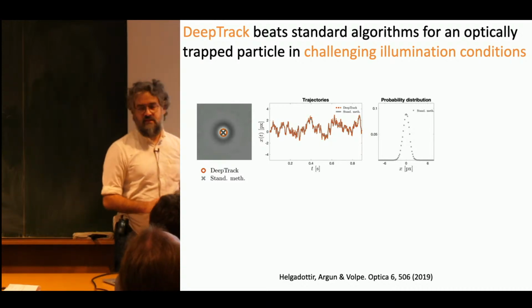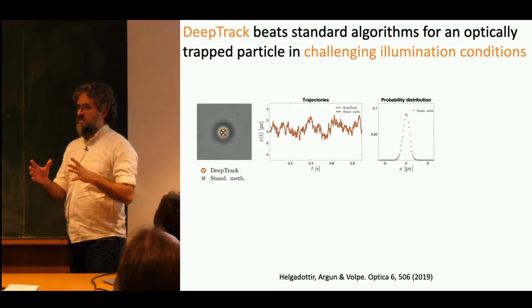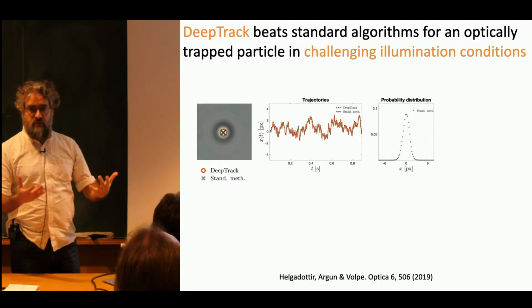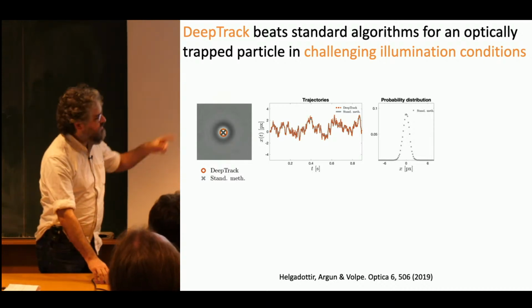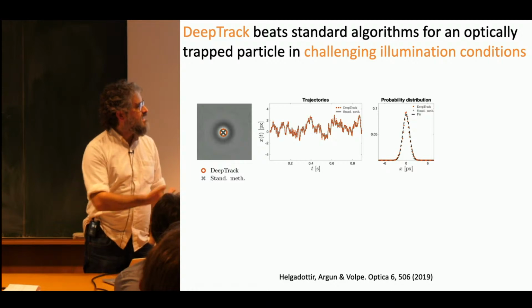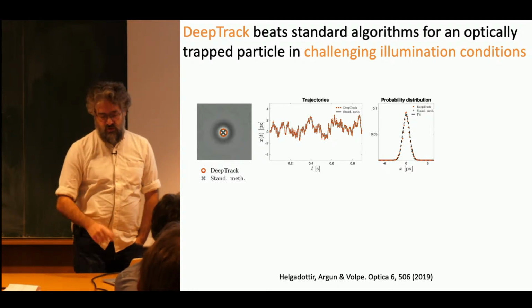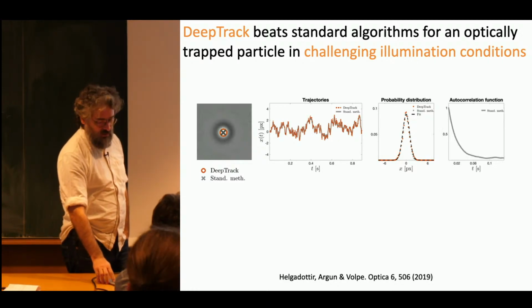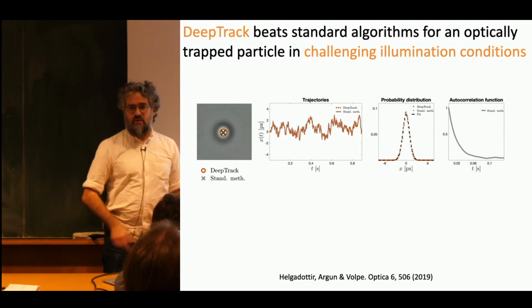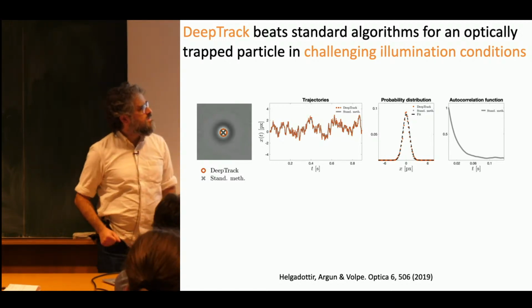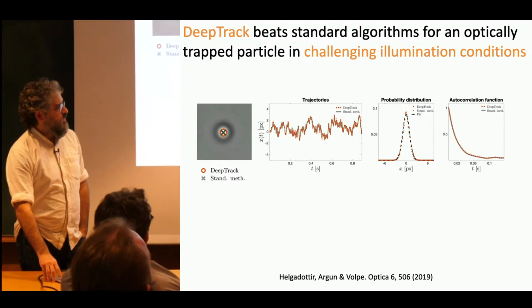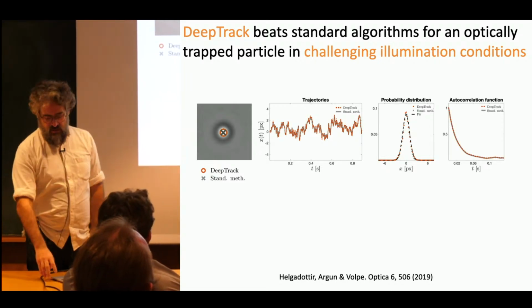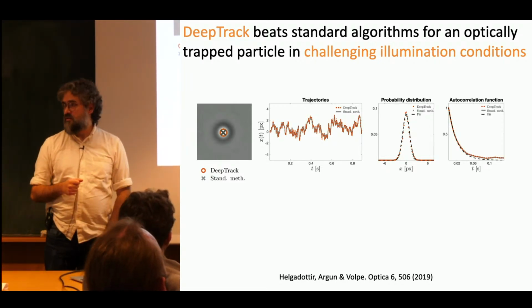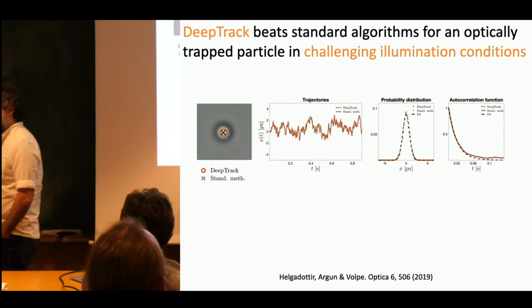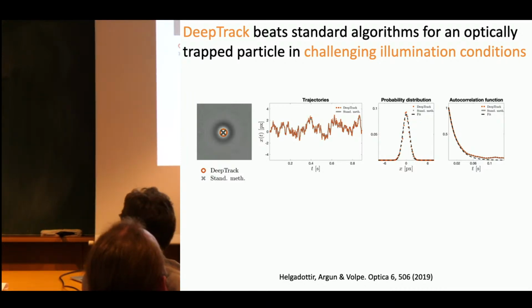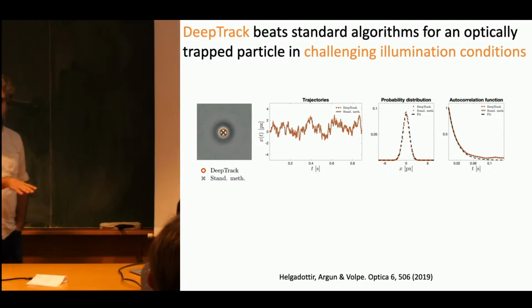And then we can also compare the distribution, which, being an optical trap, we expect to be a Gaussian. So we expect the probability distribution to be Gaussian. And we see that, in fact, the two distributions coincide and can be fitted perfectly by a Gaussian. And even better, we can calculate the correlation function of this particle in the trap. And as you can see, the correlation function is what we expect, an inverted exponential, and fits very well with the theory, the dashed line. Okay? So everything is good and well. We can track things that we could track anyway. So not very useful yet.